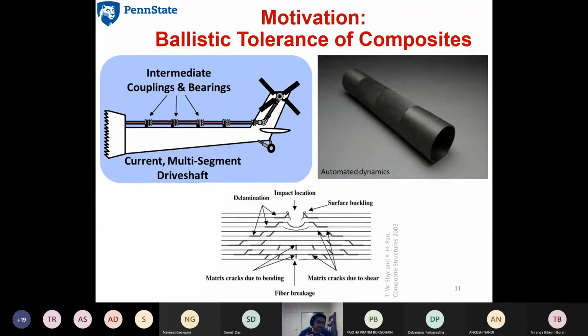At the same time, there is a need to make these materials ballistically tolerant, but you also need to make these structures very light. So you need to transition from metals to fiber composites, but you need to be aware that when you make these fiber composite drive shafts, they need to be ballistically tolerant. The type of damage in these composites is delamination, some fiber breakage, micro cracking, matrix cracking. So our thought was to improve the matrix performance in order to improve the impact tolerance of the material.